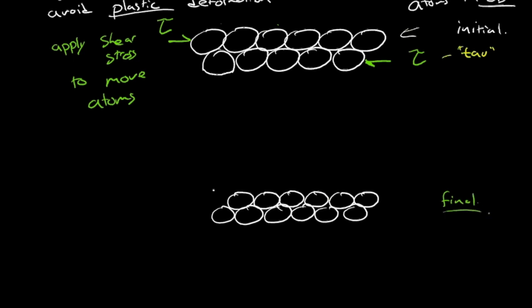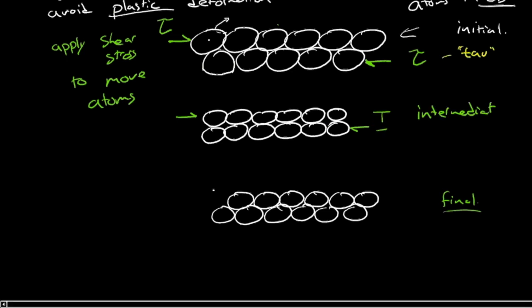But what does the intermediate position look like? Does it involve this atom here going to this sort of middle position? And I'll draw that. So here's what could be potentially our intermediate position, the state that the atoms have to go through before they get to their new deformed position. All the atoms in this row here have climbed up on top of their neighbors, essentially. This gets climbed up here, and so is the neighbor. And they've all hit this intermediate position, where they're actually spaced out further apart.